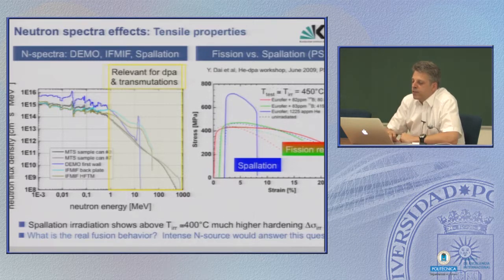If you compare this with these spallation sources, that's the artificial neutron sources, then there is again a tremendous overestimation, because here the production rate of helium is much, much higher than in a fission reactor, and also higher by an order of magnitude, at least, compared to a fusion reactor. So that's the general problem. We need irradiation data, but we cannot produce it in the way a real fusion reactor would produce neutrons.